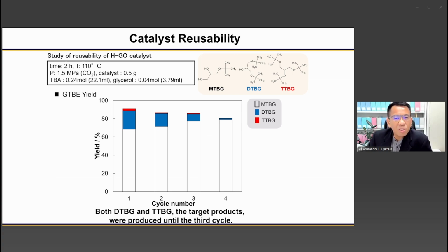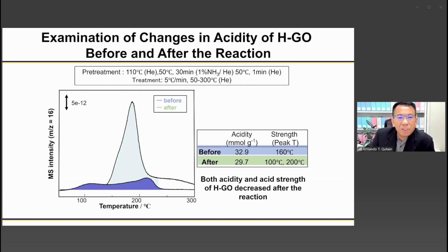With regards to catalyst reusability, we can actually use the catalyst for 3 cycles. It's really stable. However, probably because of the loss of those functionalities on the surface of the catalyst, there is a disadvantage on the selectivity of the desired DTBG and TTBG in the products. We also examined the changes in acidity of the catalyst before and after the reaction, and we notice this is actually probably the reason why the selectivity to the target DTBG and TTBG decreases.